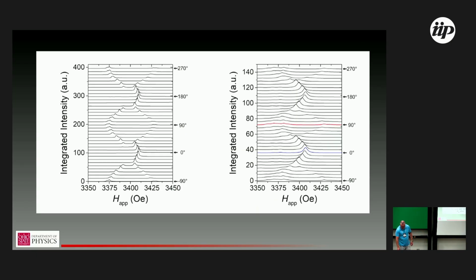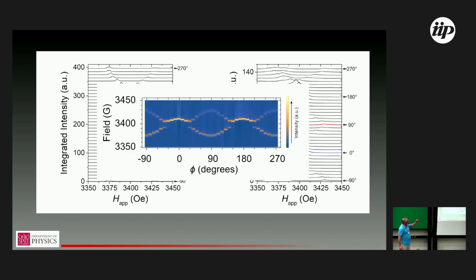And so this is just showing the same data again and really highlighting, if I now take the data into a color plot for intensity, I think it really highlights the anti-crossing behavior here. We didn't do this at the time because we were still getting our feet wet, but it would be interesting to come back and characterize the strength of the coupling of the different magnon resonances here. You can see it's quite strong. We get a really wide gap relative to the line width.